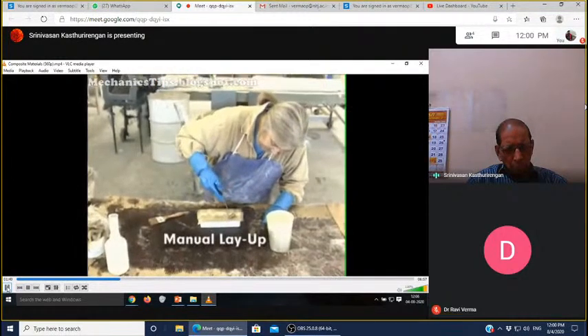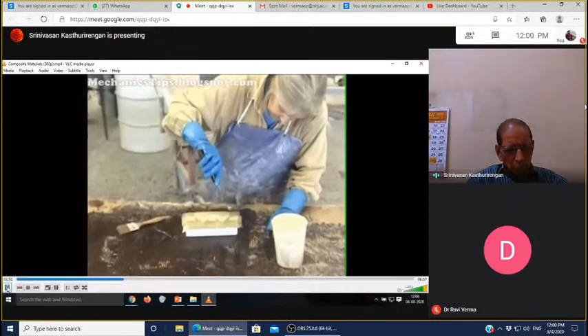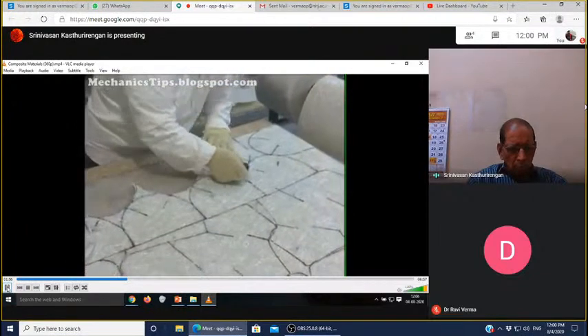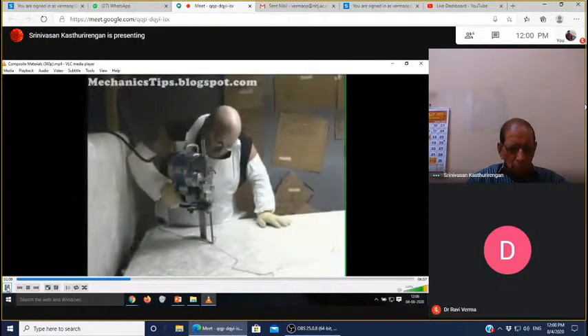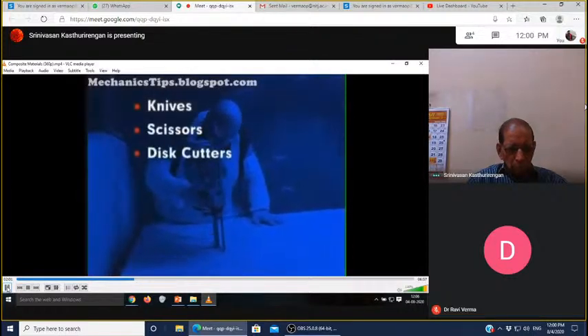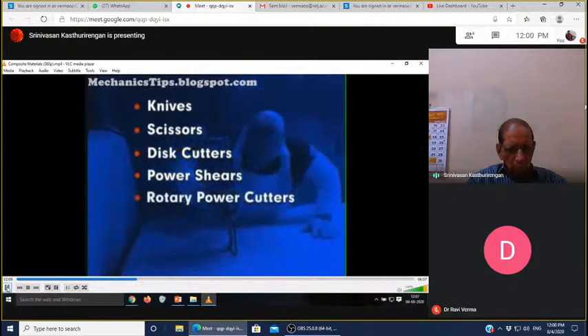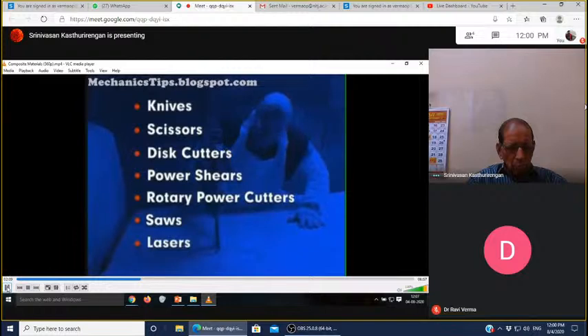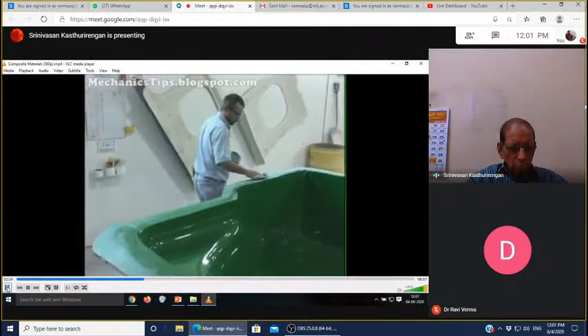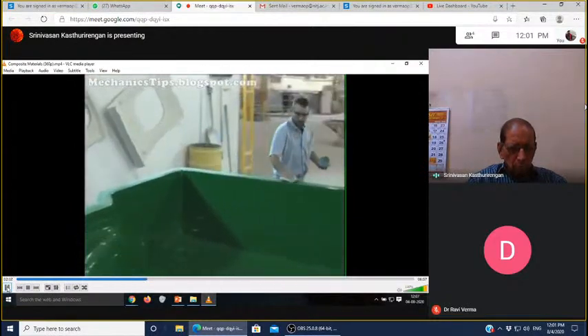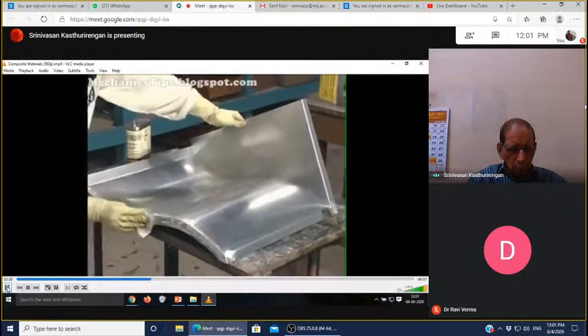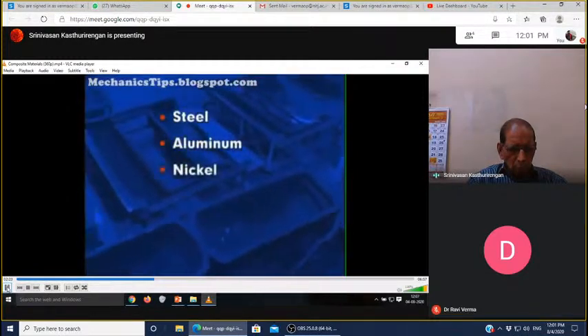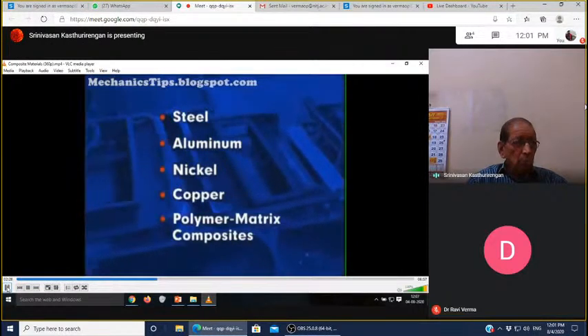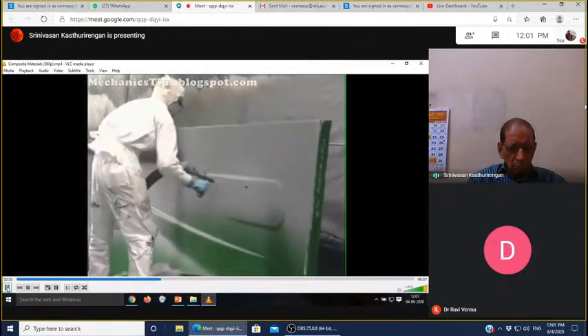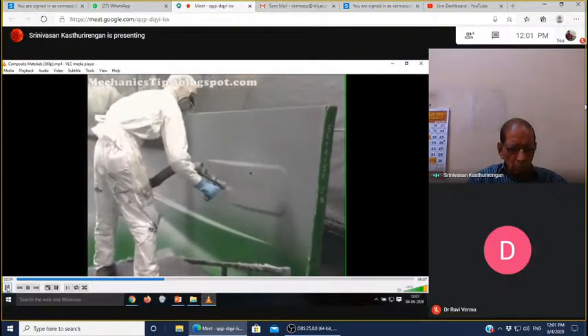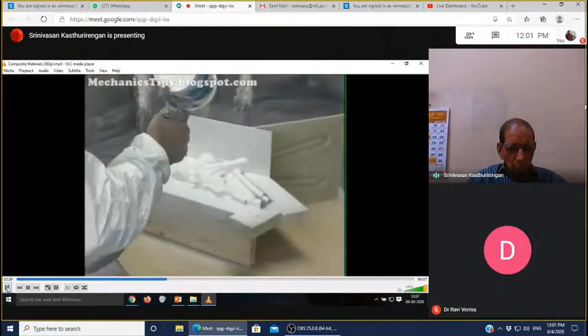Manual layup is a widely used method of manufacturing a wide range of composite parts and components. The process begins with cutting the reinforcement material to size. This may be performed using knives, scissors, disc cutters, power shears, rotary power cutters, saws, or lasers. A mold having the desired part shape is then coated with a release agent to permit subsequent part release. Composite manufacturing molds are commonly made of steel, aluminum, nickel, copper, or polymer matrix composites. Once coated with a release agent, a layer of resin called a gel coat may be applied to the mold and allowed to cure to a tacky state.